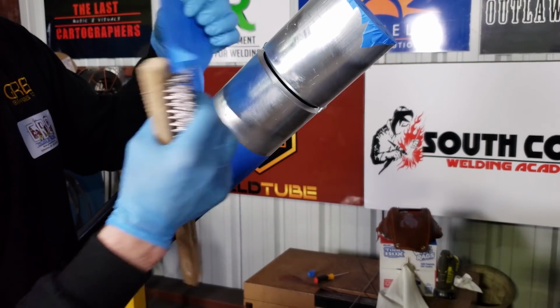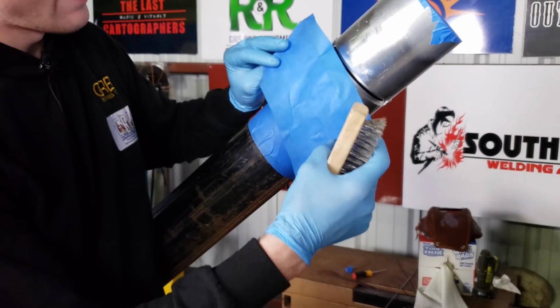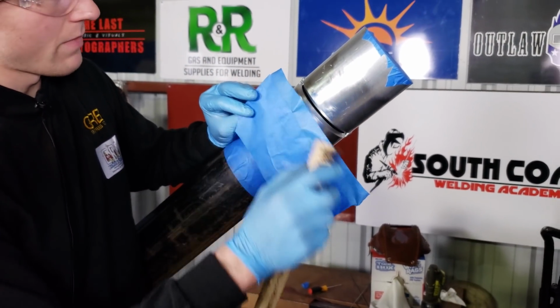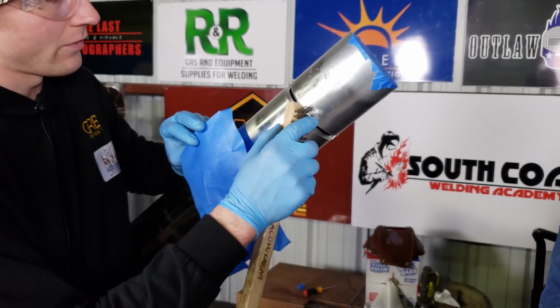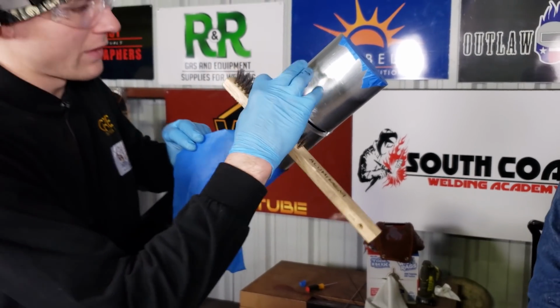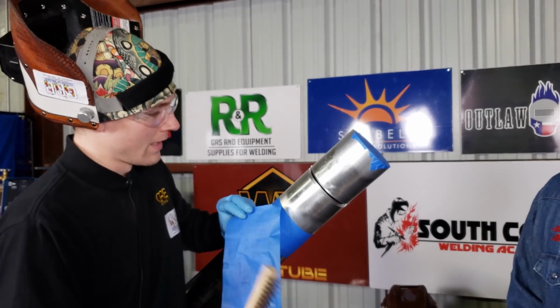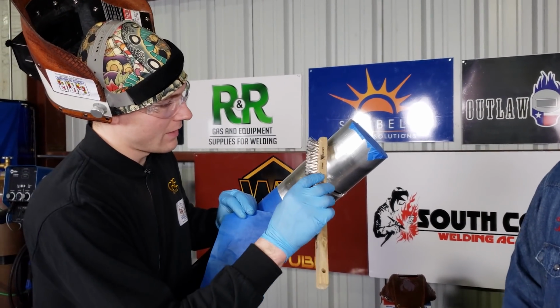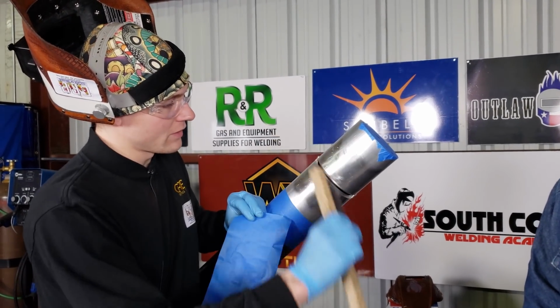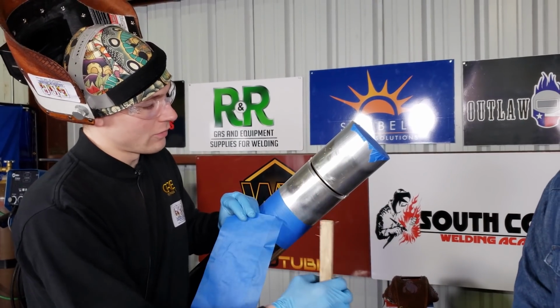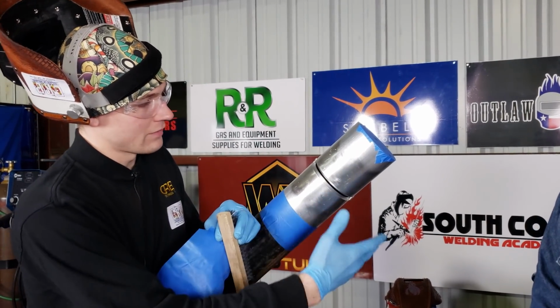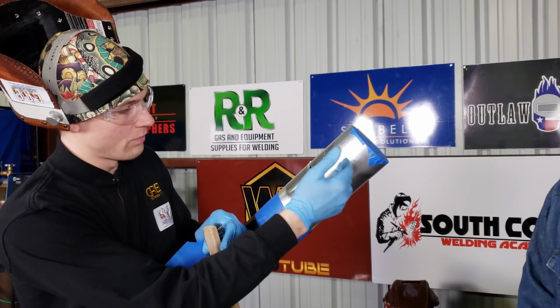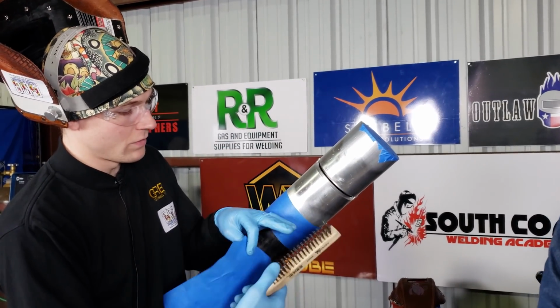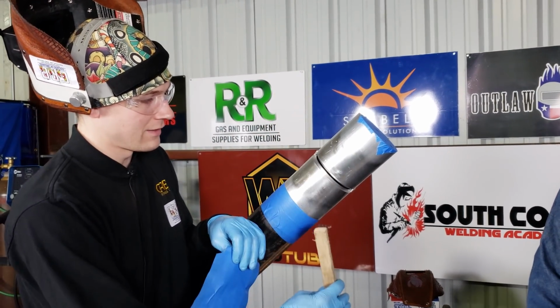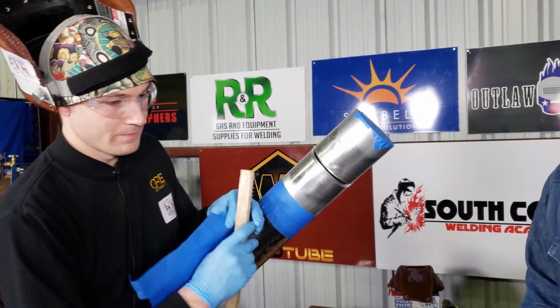The reason is that when I heat up the tape, I do not want any of this tape residue in my weld zone, the heat-affected zone, or even anywhere relatively close to the weld zone. If there's any tape residue, when I start brushing the weld zone and heat-affected zone to remove oxides, I do not want tape residue brought into my weld zone, especially if tape residue contaminates my hand brush.